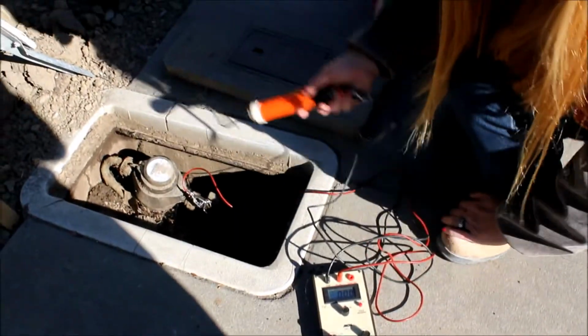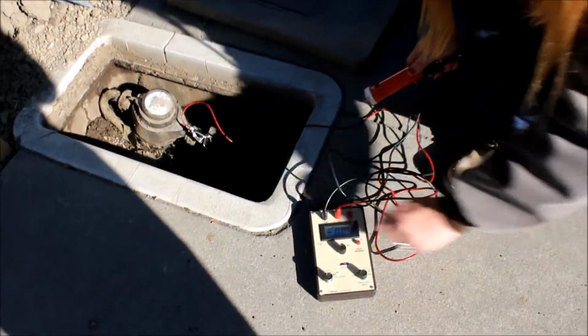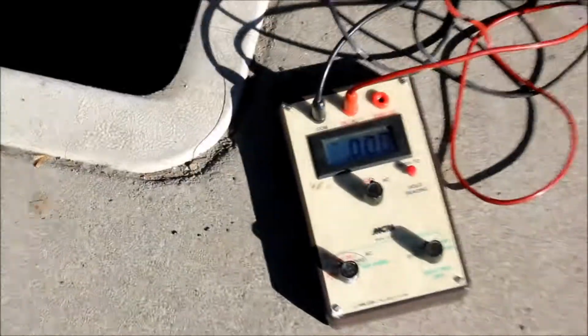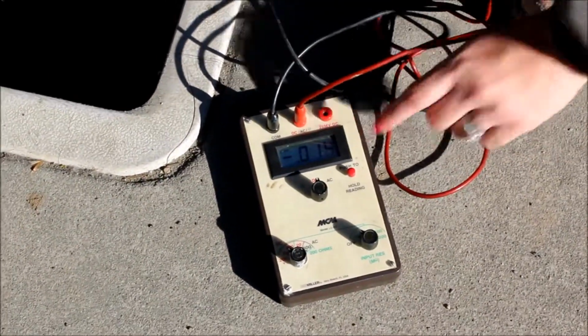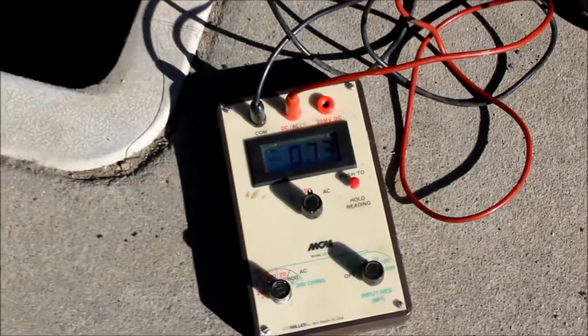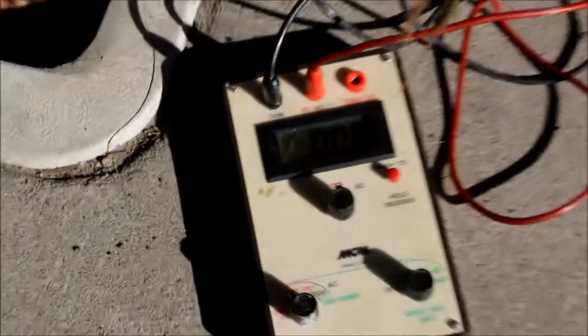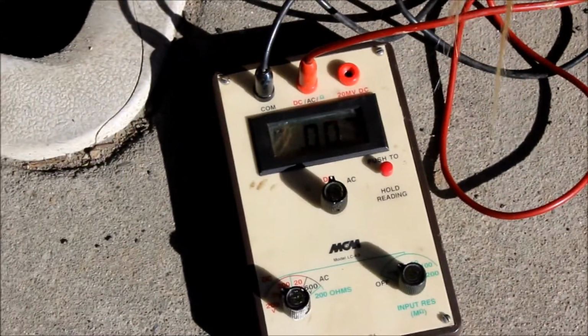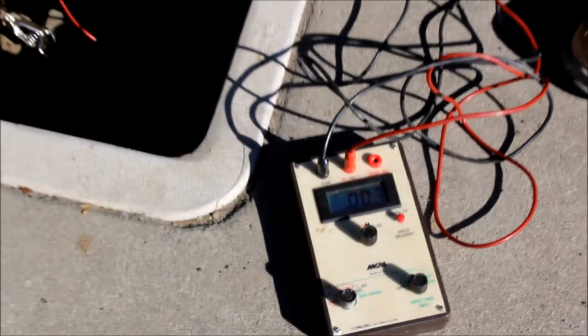So I have this set up here, and the way that I would know if this was protected is I would have at least a -700 reading, and at this point I have a 0.007, which means that this line is not connected and it's actually subjected to corrosion. Ultimately, this will have to be replaced by the city within the next 2 to 5 years.